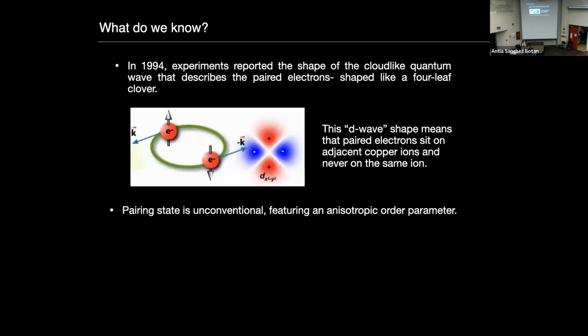And one thing that we do know, because there are experiments on this, is the shape of the quantum wave that describes the paired electrons in the cuprates. And it's shaped, as you see here, like a 4-leaf clover. This we call the d-wave shape, and it means that the paired electrons sit on adjacent copper ions, but never on the same ion. So this is already quite different with respect to what I told you before that happens in the conventional superconductors. So we say here that the pairing state is unconventional instead, as it features an order parameter that is now anisotropic. Remember that in the conventional ones, we had an isotropic one.